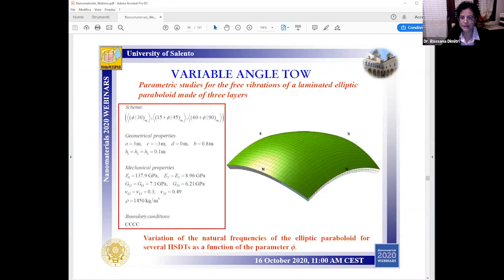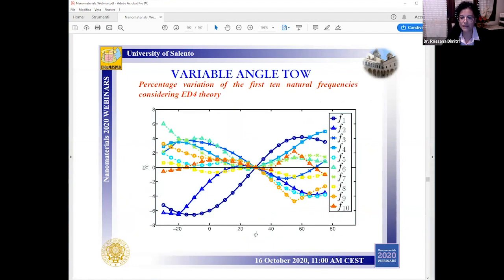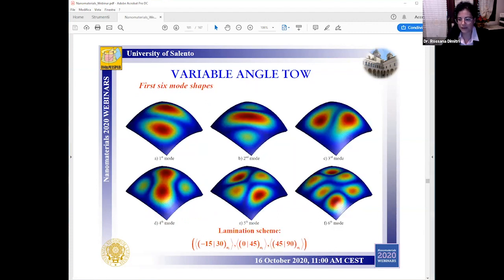So for example, let's consider a laminated elliptic paraboloid made of 3 layers, where we check the sensitivity of the vibration response, changing the parameter phi, defining the varying alignment of the fibers, and look at the variation for the first 10 natural frequencies and the selected theory, where we vary the parameter phi. And this reveals the great dependence of the mechanical performance and the structural stiffness on properly varying and tuning the reinforcing phase and its alignment within the material. And look also at the kinematic response, which is perfectly coherent with the selected boundary condition, I mean a completely clamped structure.